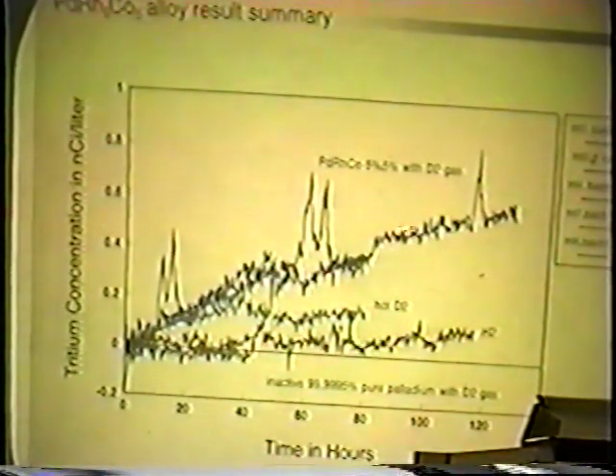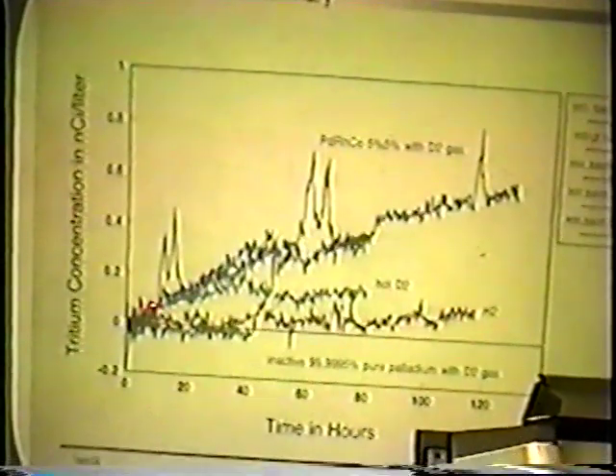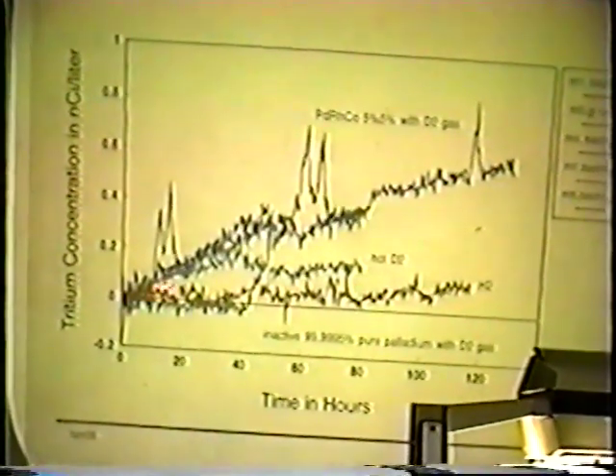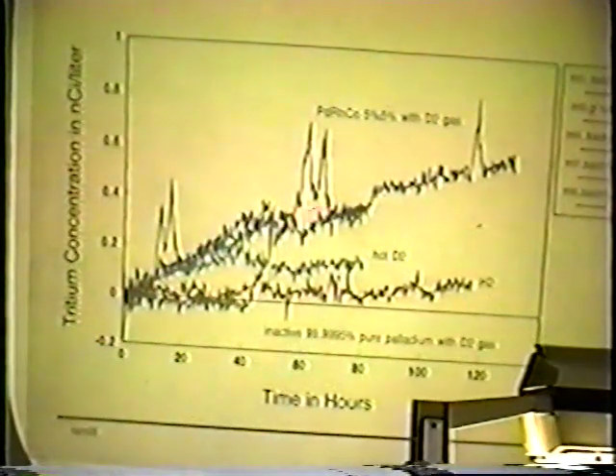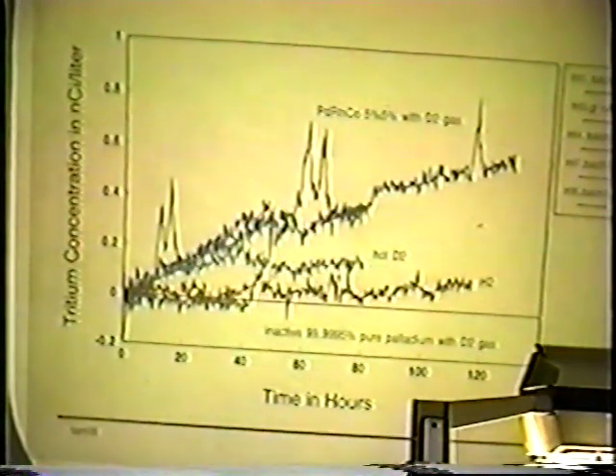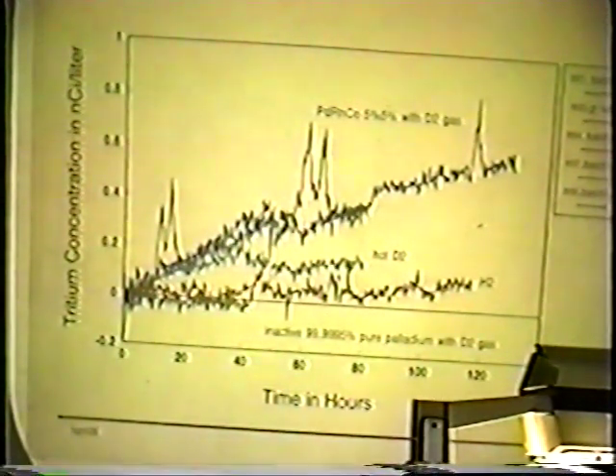And these are a couple where we've intentionally kept the current low and kept it cool, so that what we're doing is we're just generating and treating. But you can also see that there's a different slope here and here, and I think there's some slight dehydrogenating of material as it goes on. This is again 120 or so hours, so about a 6-day run for each one of these. And again, there's 4 of these sorts of runs that have been good, and then a couple of these control runs, as well as some runs where we've just heated the material up electrically.